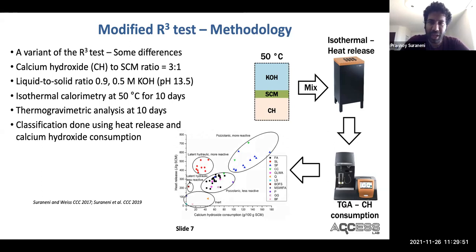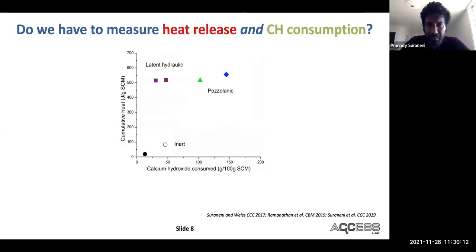Now, the differences between the R3 and the modified R3. The R3 is done at 40, the modified R3 is done at 50. The R3 has added sulfates and carbonates. The modified R3 does not have added sulfates and carbonates. I'm not going to go into details of why the differences, etc., but I will cover the temperature aspect just a little bit. Now, we are measuring both heat release and calcium hydroxide consumption.